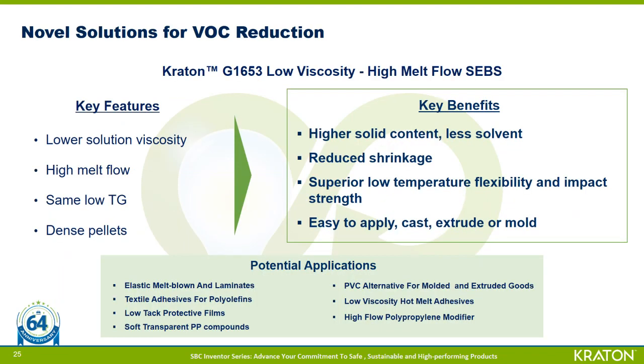Kraton's precisely controlled anionic chemistry allows molecular adjustments to make smaller molecules, which improves processing and leverages lower viscosity in the application, which can then be utilized to potentially reduce VOCs in the formulation. For example, one of our new polymer grades, Kraton G1653, highlighted here, is a low viscosity, high melt flow SEBS product. It may be of particular interest to solvent and hot melt based systems because the lower viscosity and higher melt flow enables easier processing and may offer the potential to reduce cycle times.